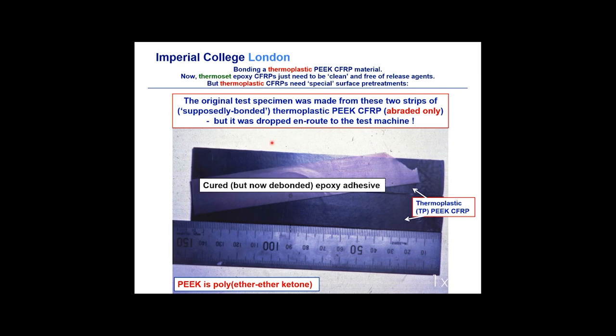This is the original sample that we made. We had 2 strips of thermoplastic, that's PEEK CFRP. We glued the 2 strips together with a purple adhesive, and on the way to the test laboratory, the PhD student dropped his sample. As it fell to the ground, it split open. So obviously the wetting and adhesion were very, very poor. In fact, you could put your fingernail under this strip of cured adhesive, the purple strip, and actually just peel the adhesive away from the CFRP.